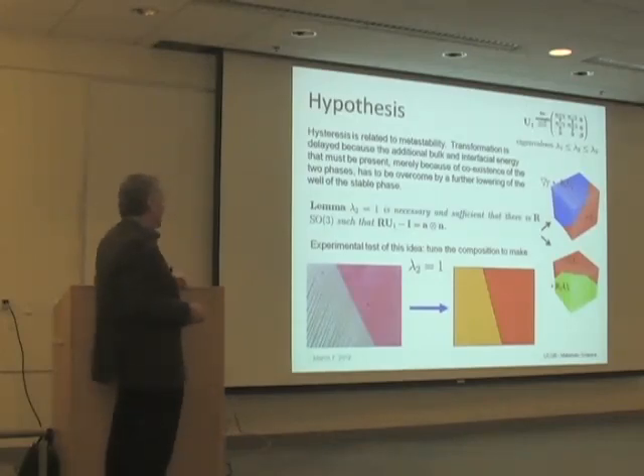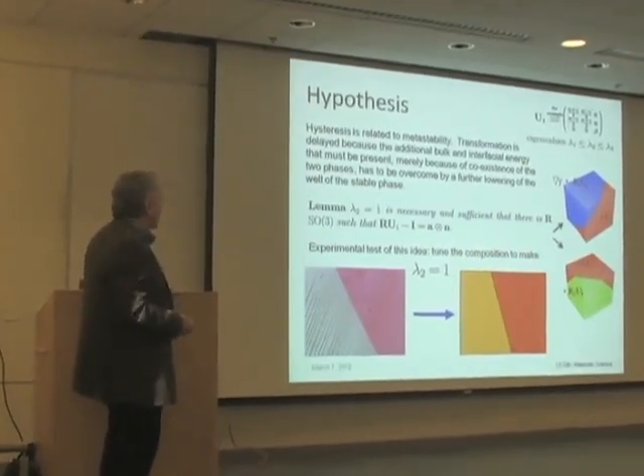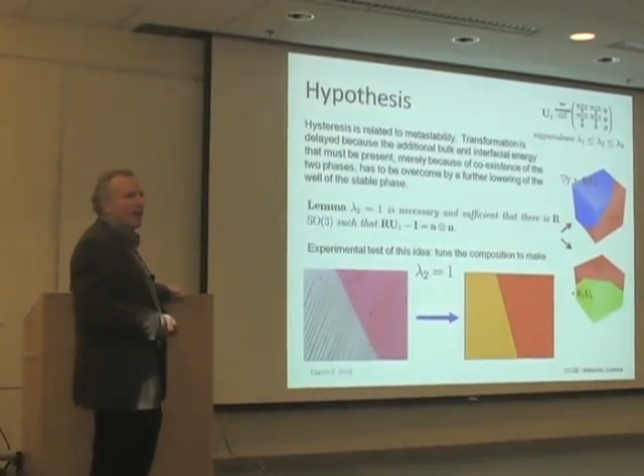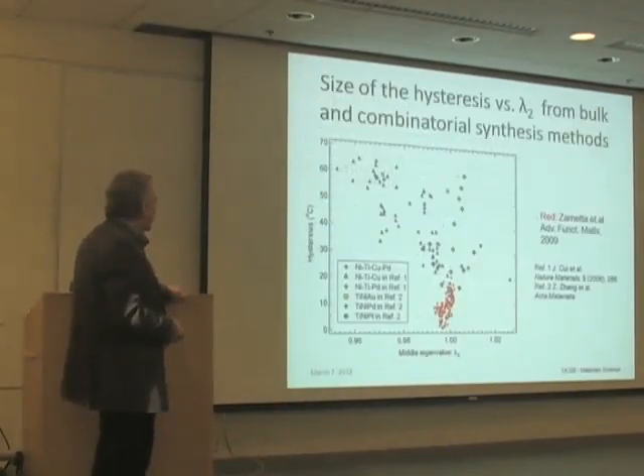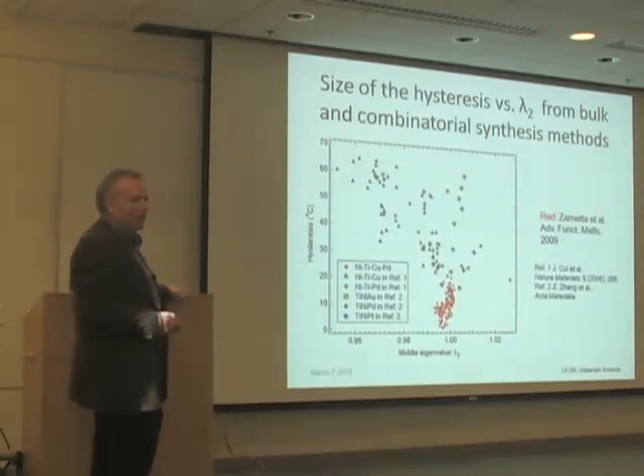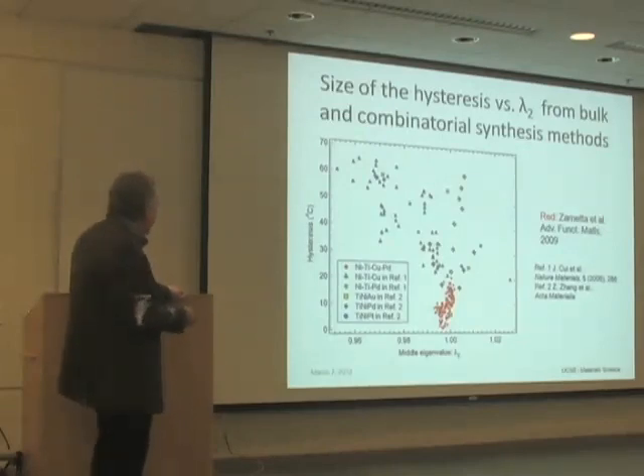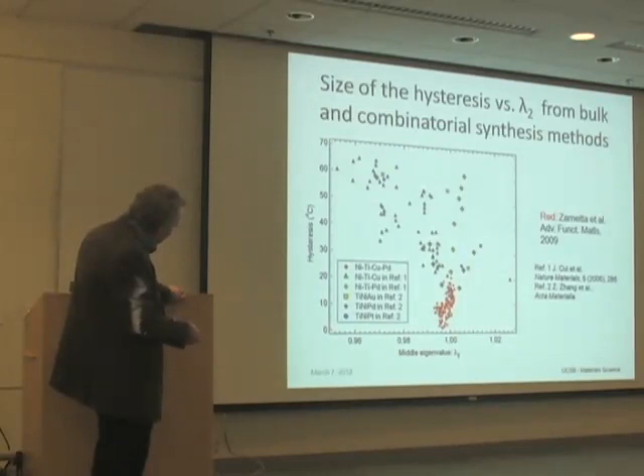Okay, so we did that, and we saw an amazing drop. This is a compilation of a lot of data. This was the first data done in my lab. Then combinatorial synthesis people got interested in this, and it's a wonderful area for combinatorial synthesis. They managed to get the hysteresis down to, not plotted versus composition, but plotted versus this middle eigenvalue, and there's one. You seem to be able to drive the hysteresis down. They got a little enthusiastic, and they said they drove the hysteresis to zero. Okay.